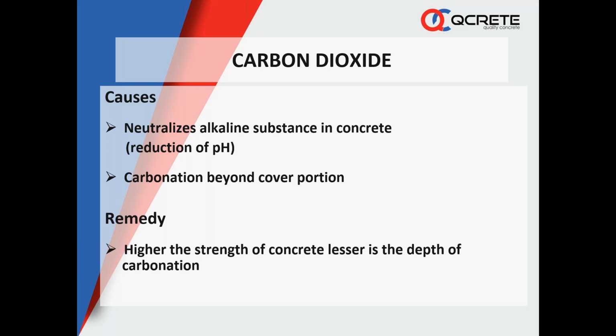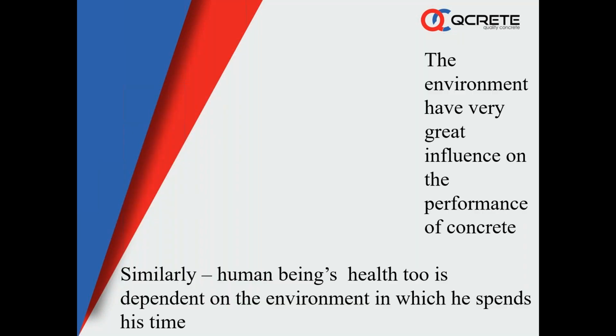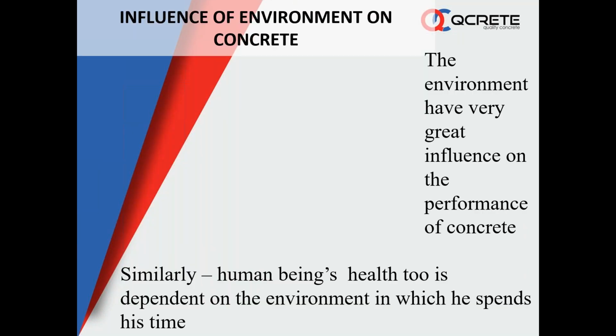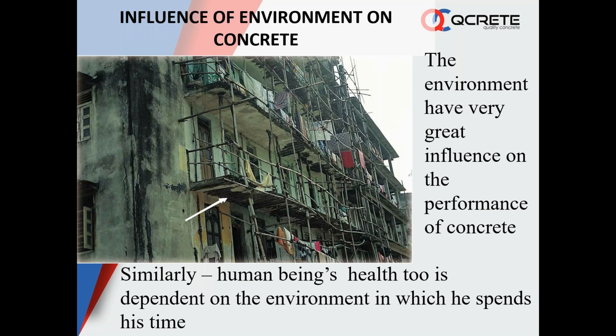The remedy is that we have to go in for higher and higher strength of concrete. Now you can see here, earlier I had shown all the balconies which are protruding outside. This is basically carbonation which has taken place. Carbonic acid which was falling on the concrete surface has reduced the pH. The steel is now exposed, because the cover we are providing is only 15 mm, 20 mm, and the carbonation goes beyond that.